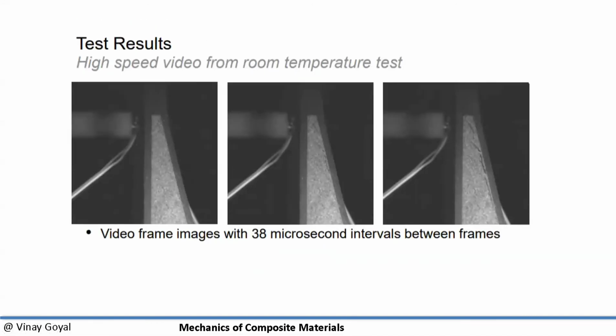Here you can see a high-speed video. I think it's important to invest in that. The high-speed video from the room temperature test is provided. Here you can see how the cracks initiate there. I'll let you look at it for a couple of seconds. So once I have that, you can see the crack initiates and propagates a little bit. And this is at 38 microsecond intervals. You can see the crack is propagating really fast across the sample.